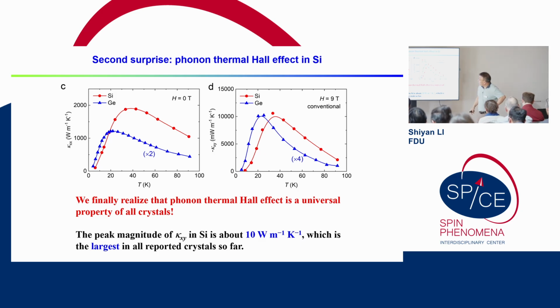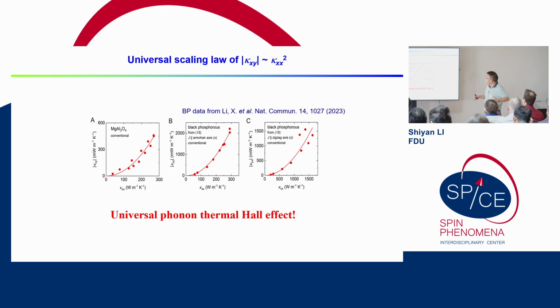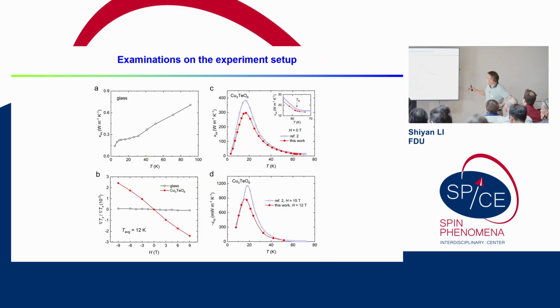But actually, when we got this conclusion, at the beginning we couldn't believe it ourselves. How can this trivial phonon contribute to such a large thermal Hall effect? Is that possible? Is there some problem with our experiment? So we did a lot of checks. First we check this glass, right? It's amorphous, so it's not a single crystal. So there's no signal, right? No thermal Hall signal.